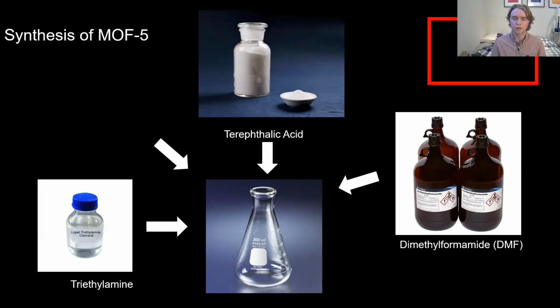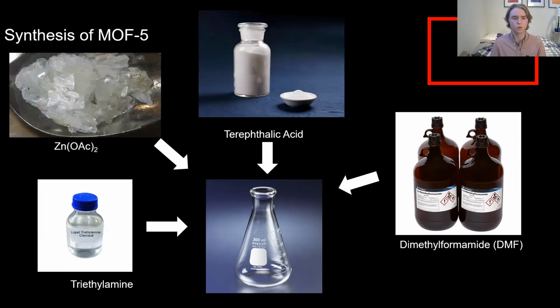And the triethylamine was there to deprotonate the acid and prepare it for chelation to our zinc. So in this case, you want to add the zinc as a solution as well. So I slowly added a solution of zinc in DMF. And depending on how quickly you add the zinc, it can actually have effects on the size of the crystals that you grow. So I was not necessarily super worried about the size of the crystals that I was going to grow, so I added the zinc pretty quickly.